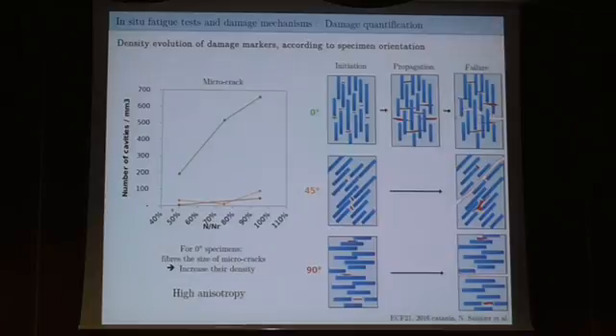For example, I show you for microcracking. I tell you for microcracking 0°, we have much more microcracks. From this analysis, effectively, that's what we obtain, which means that for 45 and 90° specimens, we have almost no microcracking, while we have a lot of microcracks for 0° angle specimens. And the reason is that finally we see that it's very hard to propagate the crack in the 0° layer. And it's very easy in the 90 or 45 because you just have the matrix to go through. You don't have the fibers to go through.